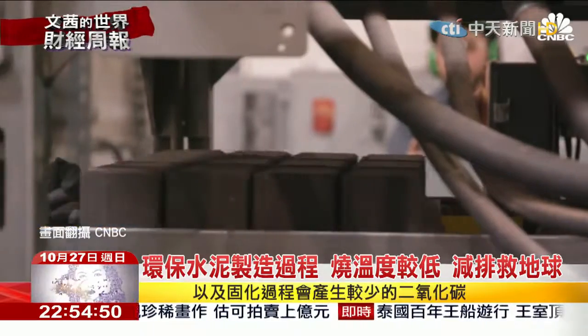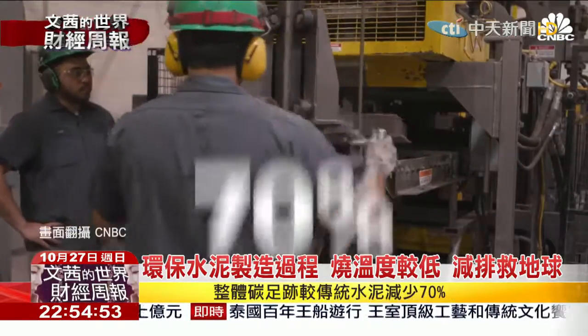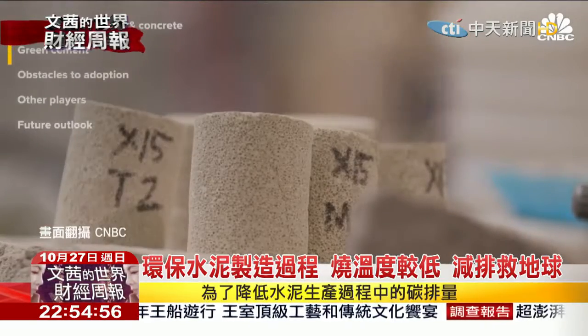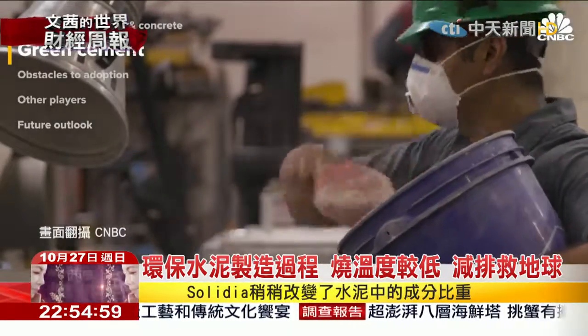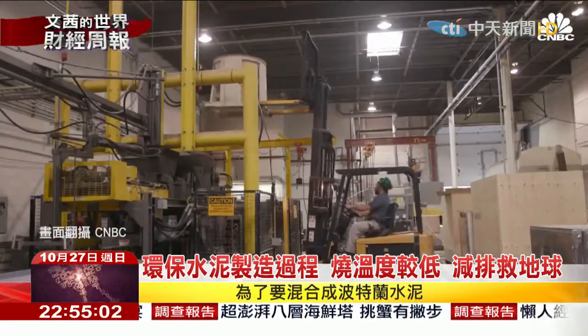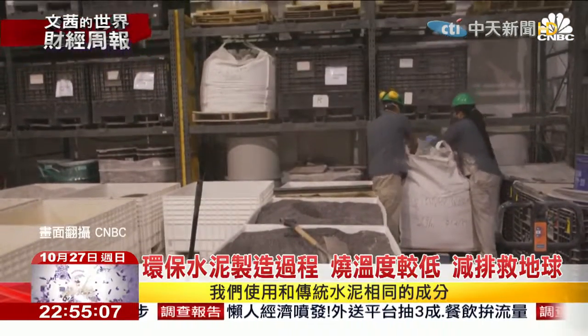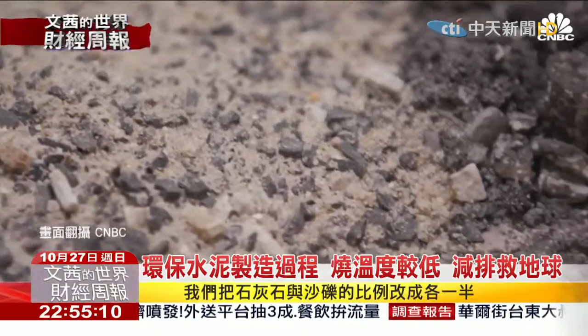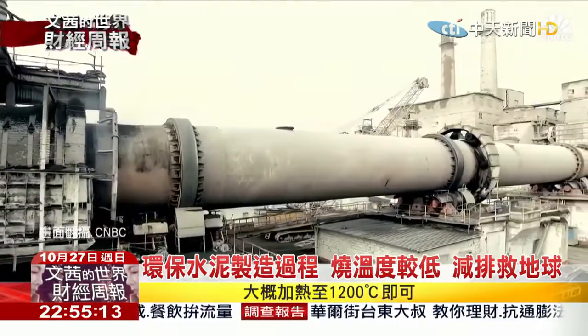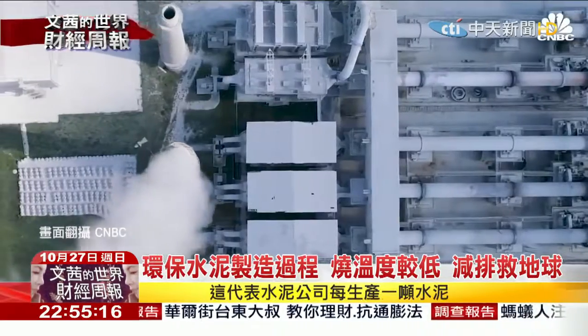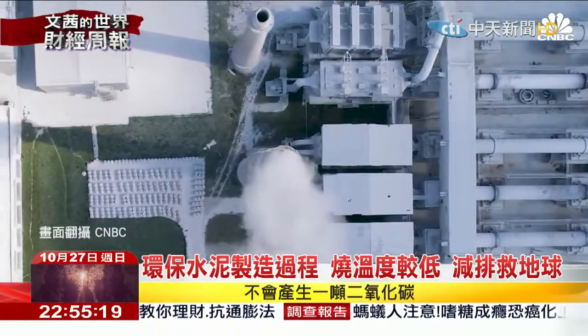Solidia says their cement mixture and curing process can cut CO2 emissions by up to 70%. In order to reduce the carbon footprint of its cement, Solidia Technologies had to slightly alter the chemistry of the mixture. In order to make Portland cement, you use limestone and sand. We take exactly the same raw materials, but we change the recipe a little bit. We mix it about 50-50, and that reaction happens at a much lower temperature, about 1200 degrees Celsius. Now, what that means to the cement company is instead of emitting 1 ton of CO2 for every ton of cement, they emit about 40% less than that, and they use 30% less energy to make that same amount of cement. They also get more cement with the same amount of raw materials.